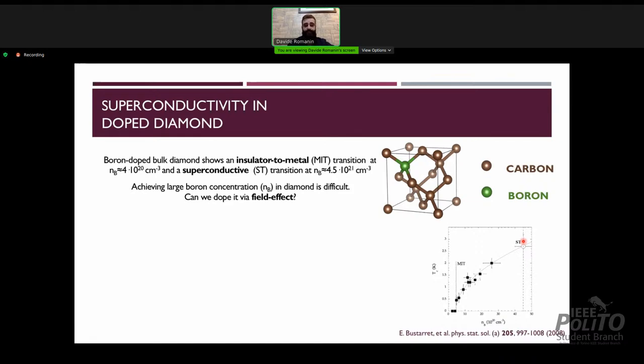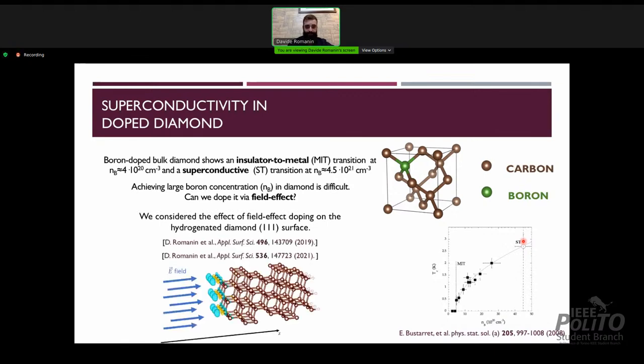We tried to answer this question in diamond thin films along the 111 direction, more specifically in these two papers. And why did we choose the 111 direction? Because it is the one that in principle should be able to accumulate as much charge as possible with respect to the other two. Now, we have studied three doping regimes: low, medium, and high. Let's start with the low doping.